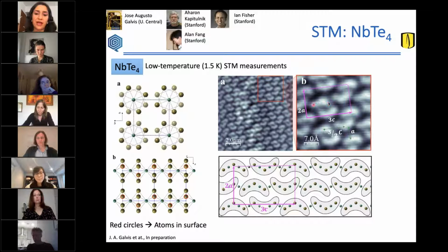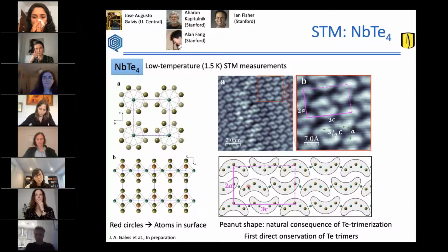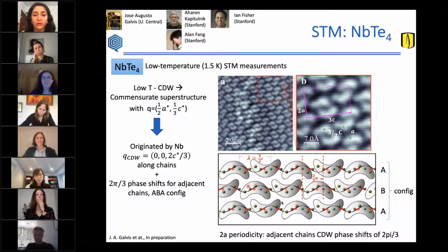in which you see these very nicely peanut-shaped entities, which are actually formed by tellurium trimers that are observed on the surface of this compound. When you cleave it, the surface is formed by tellurium atoms, which form trimers, and given their zigzag organization within the surface of the material, and because of these chains, given their quasi-1D character, we can see a superstructure formed by these trimers, which has a periodicity given by this drawing.